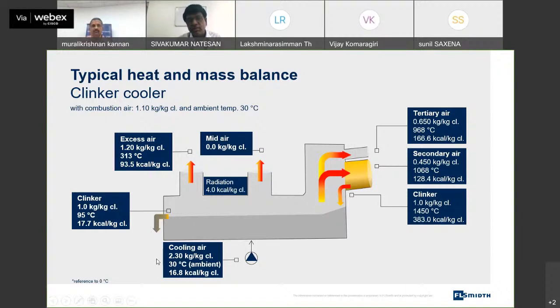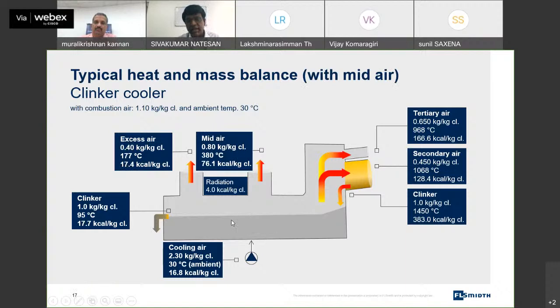And you can see that some of the coolers in the market use more airflow, maybe 2.5 kg, 2.6, but at a lower pressure, because it's like a grate plate cooler, and that will result in excess airflow being higher and temperature also being lower. They may be able to save some power in the cooling air fans because of low pressure operation, and our fan power may be slightly higher, but the benefit of the slightly higher fan power is from the MFR control, and also the high quality heat you are going to recuperate in the recuperation zone, and also in the remaining portion of the cooler.